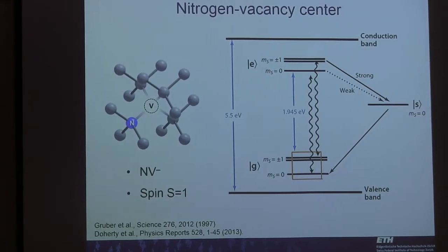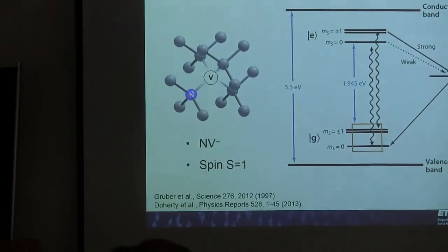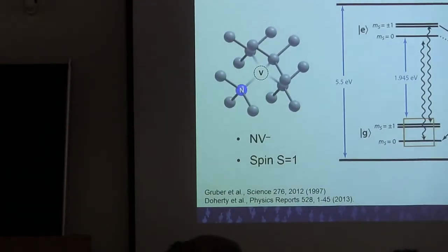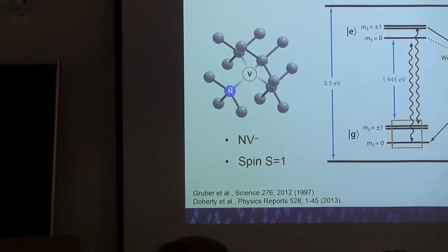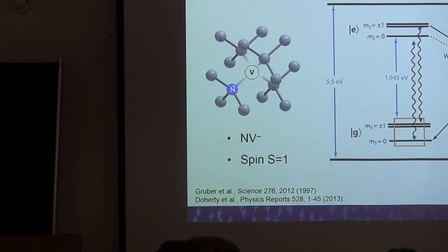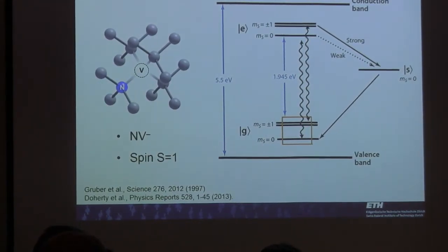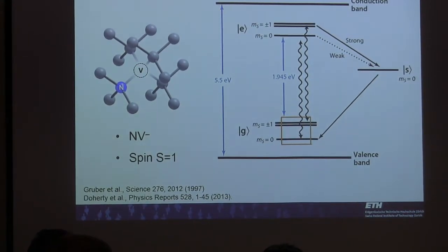What's the linewidth or the lifetime of the zero phonon line? Okay, good question. I don't know. Usually those are short-lived, picoseconds in this case. But I guess you could go through a mode analysis of the photons. What really happens when you excite the NV center is that it has some electronic wave function, which in this case is mostly vacancy. If you go to the electronically excited state, the wave function changes. This change in wave function will push out the carbons around here. So in some sense, you create a wave or some excitation in the carbon lattice, which are your phonons. It comes from a spatial change of the wave function going from here to here. But in the case of the zero phonon line, there are no phonons created. It's a rare event. In most cases, phonons are created because the wave function changes. Yeah, it's about 1% usually.